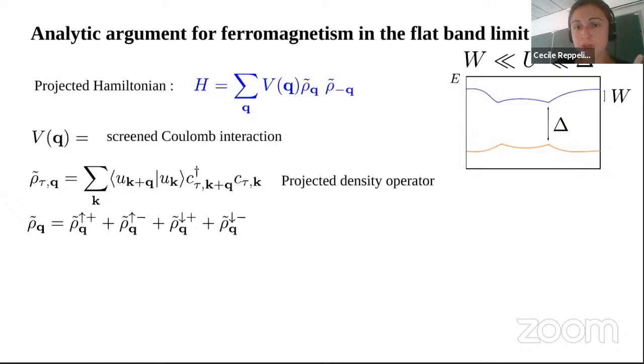So, an argument why there should be ferromagnetism at integer filling in the flat band limit. The first very important point is that the projected Hamiltonian is positive semi-definite. You can see it if you realize that rho of minus Q is equal to rho Q dagger. So when you do an operator times this operator dagger, this is positive semi-definite. V of Q is positive because we have a repulsive interaction. So H is a sum of positive semi-definite operators, meaning that the whole spectrum of H is going to be positive or zero.